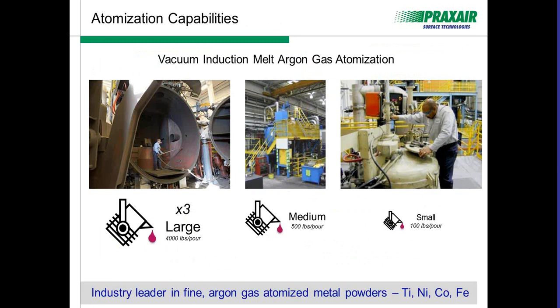We don't typically disclose our yields per se, but we do have some experimental data that we're willing to show, that with this type of technology you can maintain yields around 70% within that range if you know what you're doing and if you've engineered it correctly. And the key then is to maximize your repeatability. Use productivity tools.